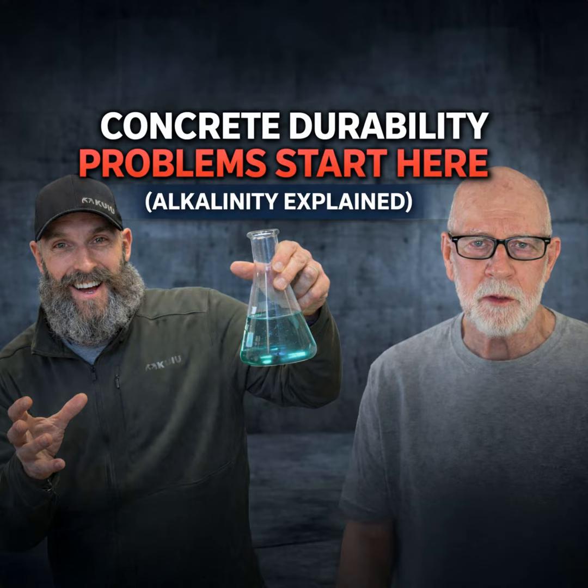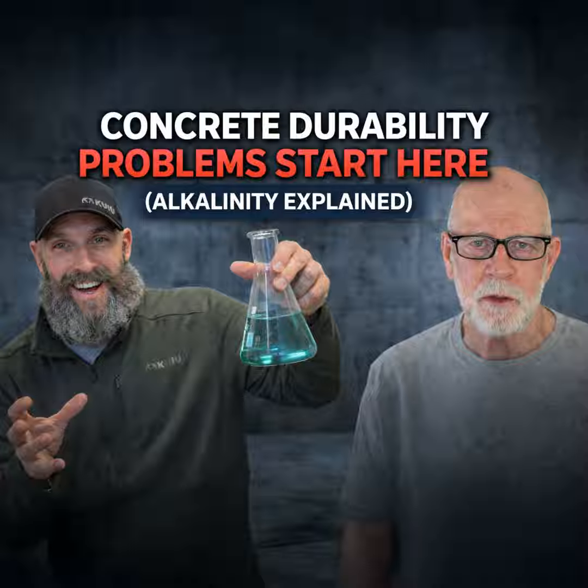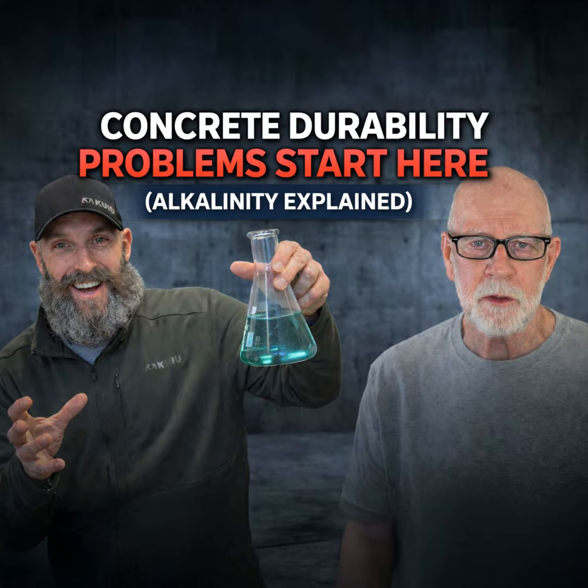But the severely damaged ones, there were areas where I added and it started to overflow and I couldn't add any more, and the pH is still 11. Well, that's alkaline. The other one's a high pH, but it isn't alkaline. The alkalinity and the damage corresponded with each other very, very closely. But just plain concrete, it will dry it out and will crack it. It will cause warping because it responds more to heat than it did if it stays wet. Because if it stays wet, at least it's swollen, but it won't stay wet.